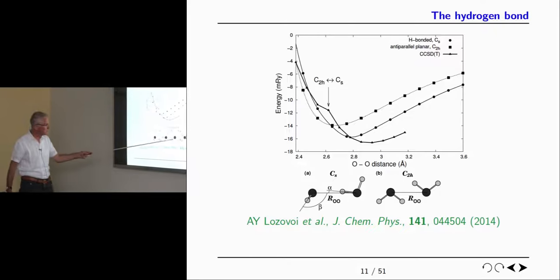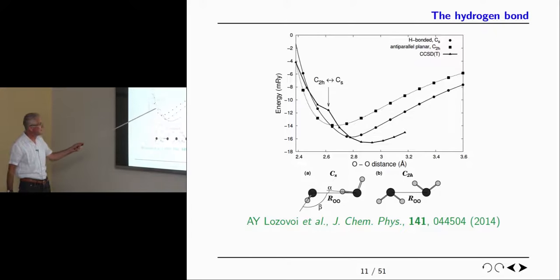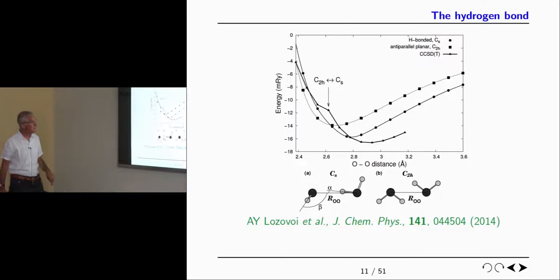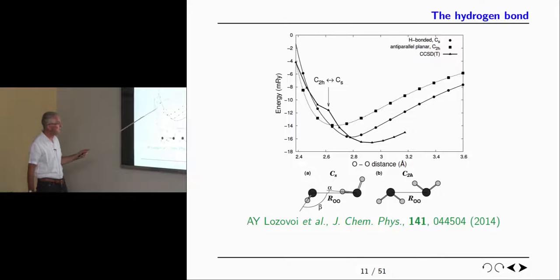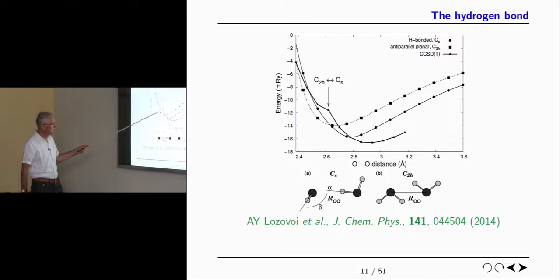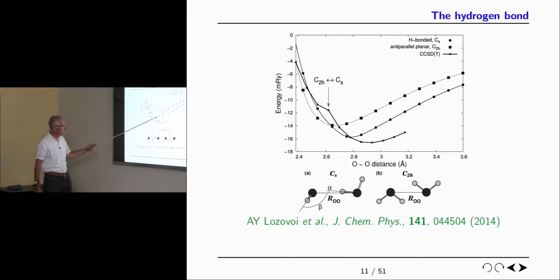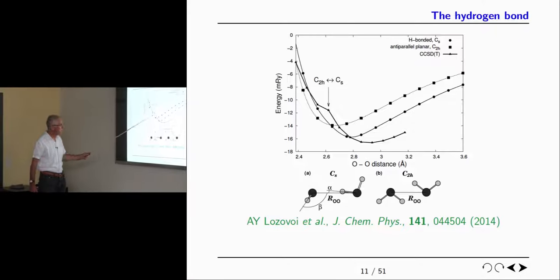In fact, they do. That is the structure of the molecule at very short distances, as we know from coupled cluster quantum chemistry calculations. But our tight binding model also reproduces that. So here's the energy versus oxygen-oxygen bond length in the case that it's in this configuration, and here's the energy versus bond length in the case that it's in the standard hydrogen bond configuration. And there is indeed a crossover, and these are the coupled cluster results. So it's very consistent with that. So we had to do further work in fitting the oxygen-oxygen hopping and the pair terms in order to get a reproduction of this result.